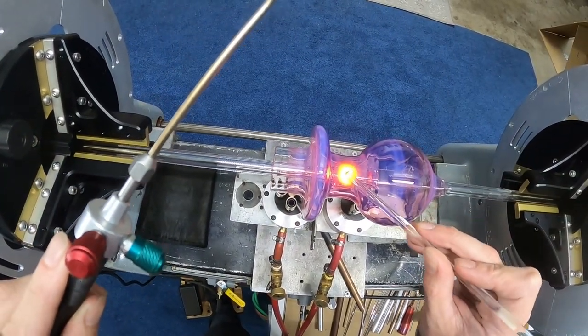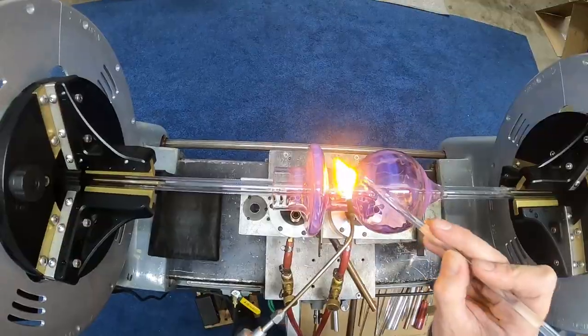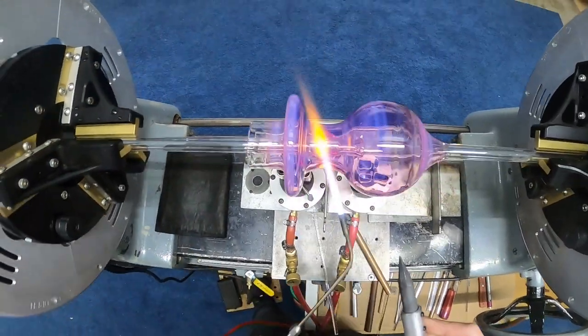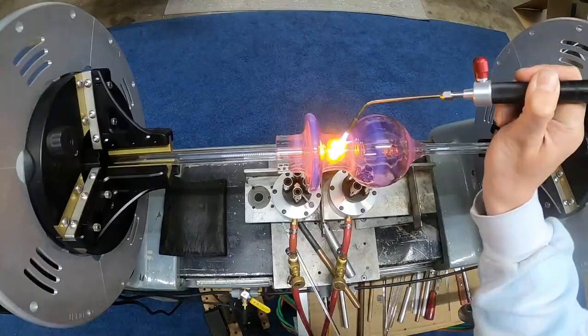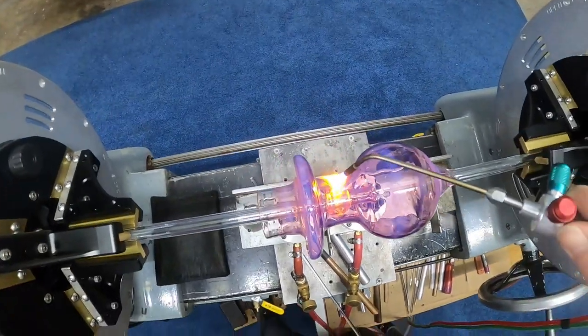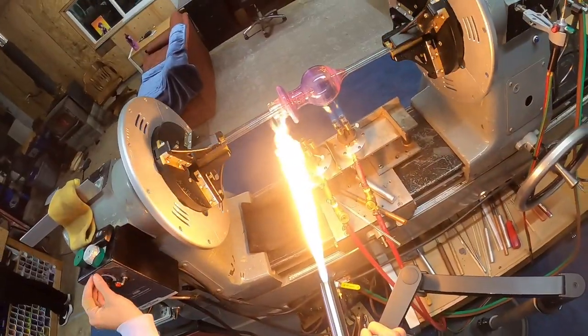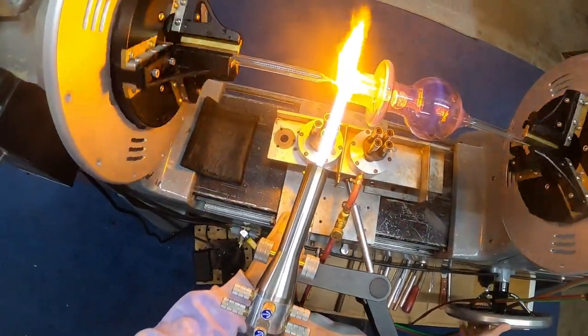The next thing is just ripping open that hole. You kind of want to make sure you don't get it super thick, just so it's easier on the melting — that's why I stretched that part out before, just so it's a tiny bit thinner. Once you rip the hole open, go in there and melt that sidewall. Use a reamer a little bit if it gets too small, open it back up. Just cook in the sidewalls and you'll see the crease disappear as soon as you melt it all the way in — and it looks really clean.